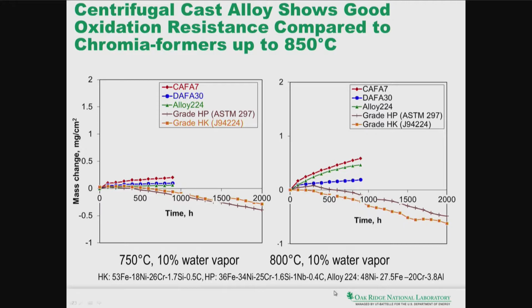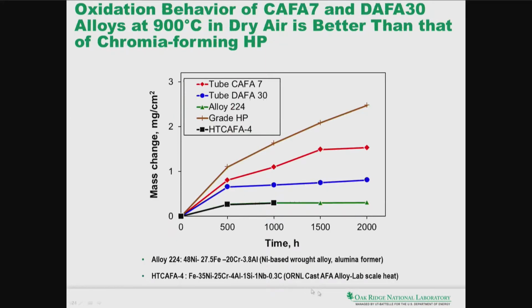good oxidation resistance. Now going up to 900 C, we show data in dry air that is devoid of water vapor. Now you start seeing some more differentiation. The grade HP alloy, as you can see here, performs the worst amongst this group of alloys. Again, the CAFA 7 and the DAFA 30, the alumina-forming alloys developed by Oak Ridge, do good, and probably the best to target for is the alloy 224 under these conditions.